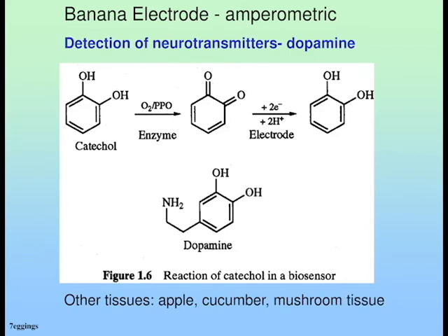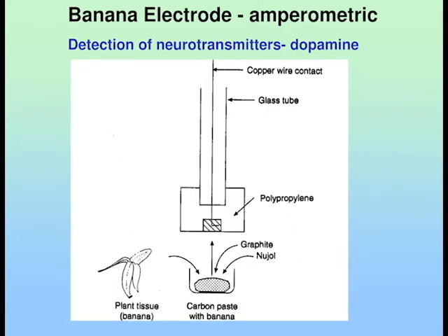If you look at the next thing, in this particular case, copper. So literally no immobilization. In fact, it's just a physical mixing. No chemicals involved. I just put graphite. Graphite is just powder. If I put graphite powder and banana, would they gel? Not so good. I need a bit of neutral oil, like silicone oil, to gel them. Take note, graphite powder is too powdery. It flies everywhere. We always have to use some oil to put them together.